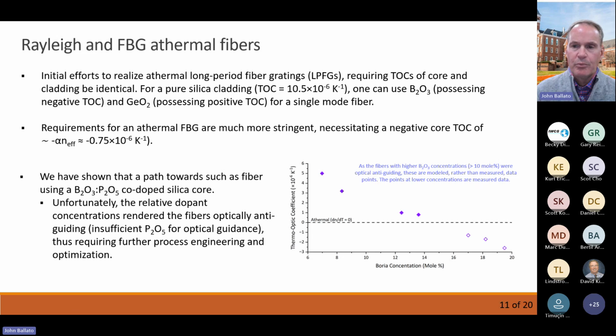To first order, you can do this with boria and germania, which again are common dopants that you can use or do use in many commercial fibers. You see in the graph below, those are actually data points from fibers that we made at Clemson. The solid diamonds are measured directly on fibers. When you get to the right at these high concentrations, the effect of boron oxide, B2O3, in silica is to reduce its index. It reduces the thermo-optic coefficient, but it also reduces the index. When you go to too high a concentration, the doped core has a lower index than the undoped pure silica cladding, and so it's an anti-guiding fiber.